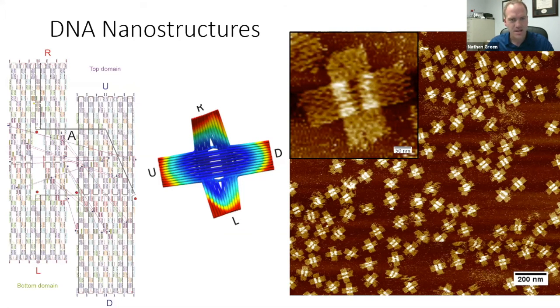So for me, the overarching theme of all these things that's been so nice is seeing how we can fine tune control of these structures. When we want to make gold nanorods, we can switch out small things that are put in the solution and we get a large gold nanorod or a small gold nanorod or a sphere. With the DNA origami, those are hugely gratifying to be able to see.